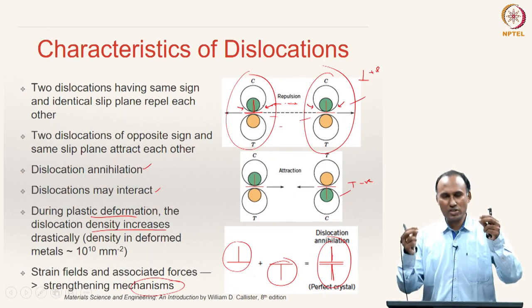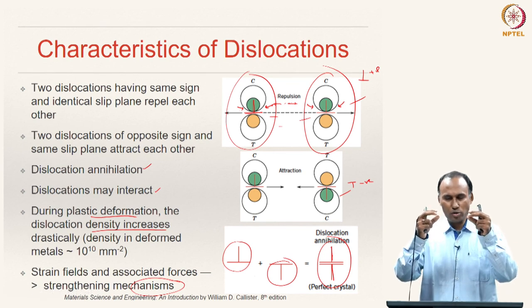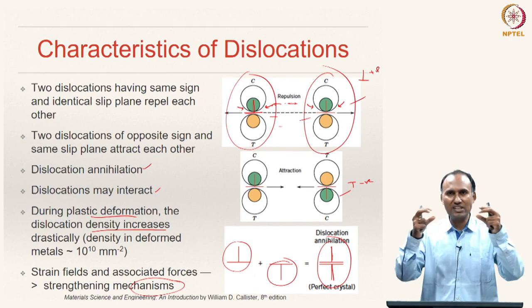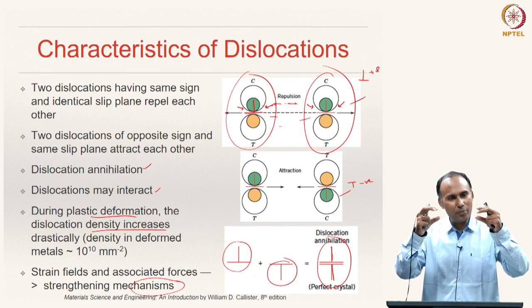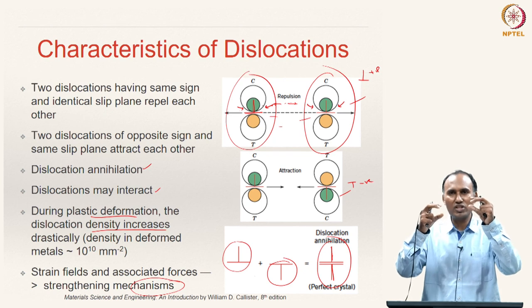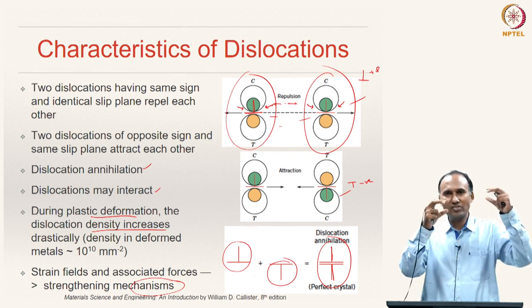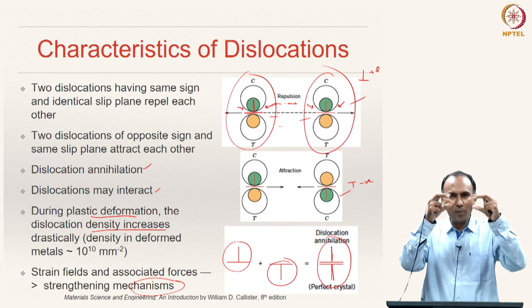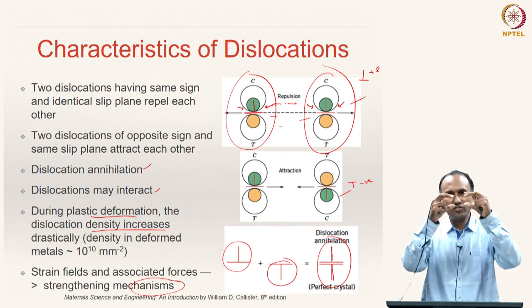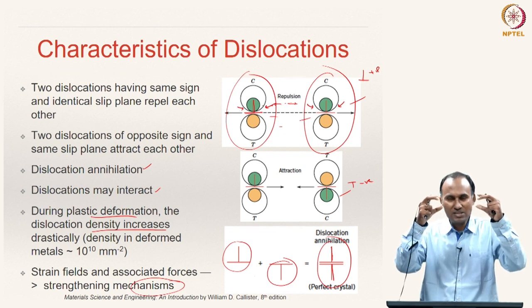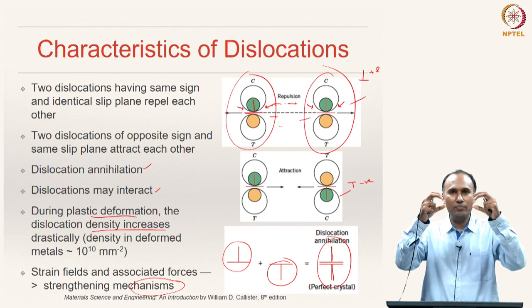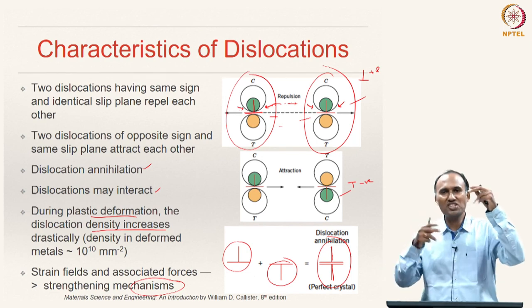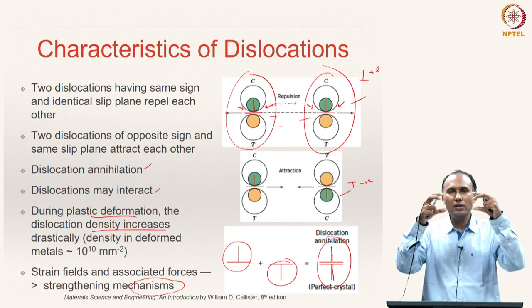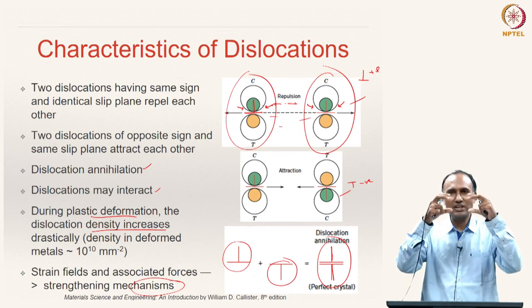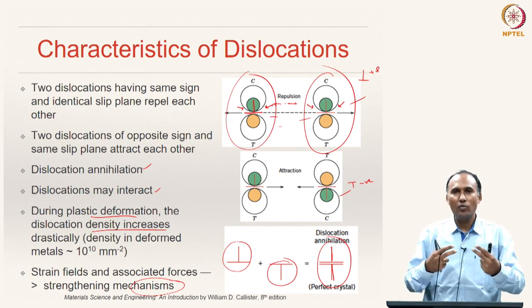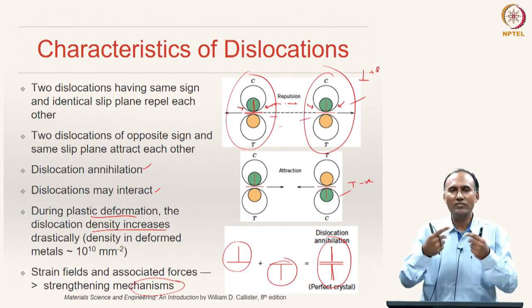Basically, when dislocations of the same sign come together due to plastic deformation, they start repelling each other. That means the dislocation motion, which would have happened if the other dislocation of the same sign was not there, would have moved this way. But because there is another dislocation, the further deformation of these two dislocations cannot happen. The dislocation motion is impeded, and that will require additional higher strain to overcome the resistance offered by these repelling force fields of the same sign dislocations, and that is what is seen as an increased strength of the crystal lattice.